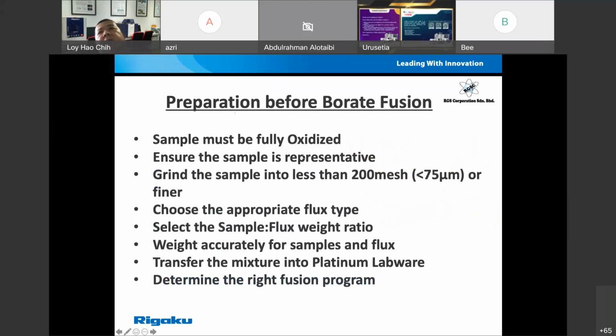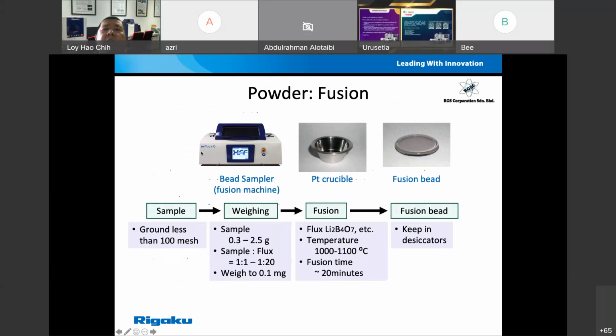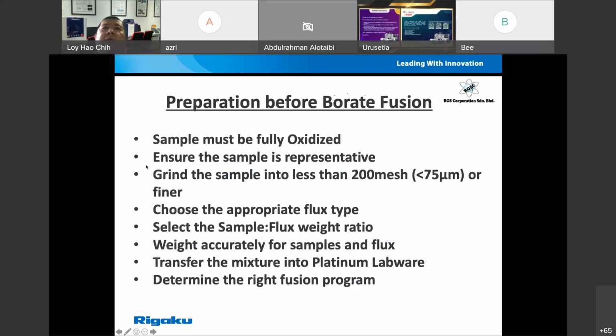The first thing is that your samples must be fully oxidized. You must ensure that your samples are fully oxidized. And secondly, your samples must be representative. This means that when you sample out from your sample batch, the sample must be representative of the whole batch. Your samples must be ground to less than 200 mesh or less than 75 micron or finer. So if you can grind it to 44 or even less than 50 micron, it will be good.